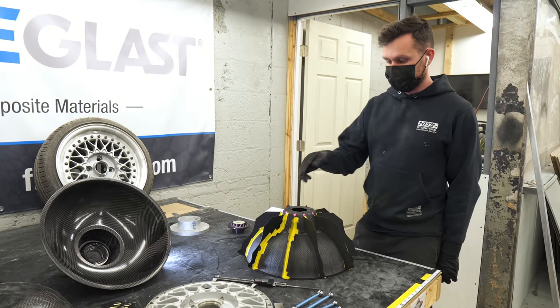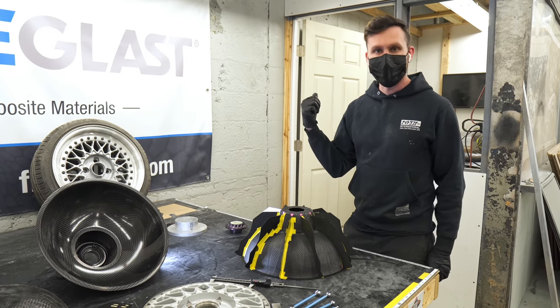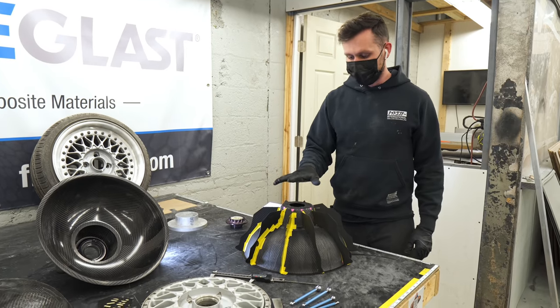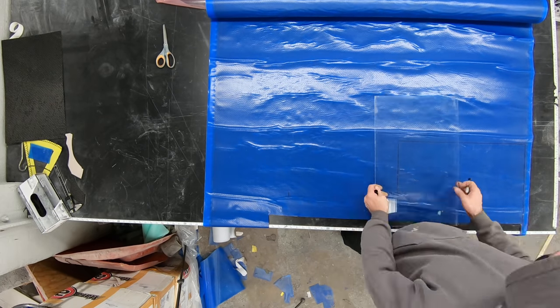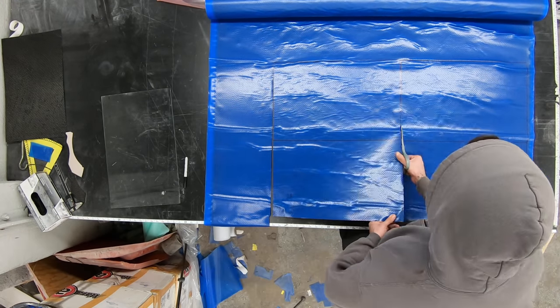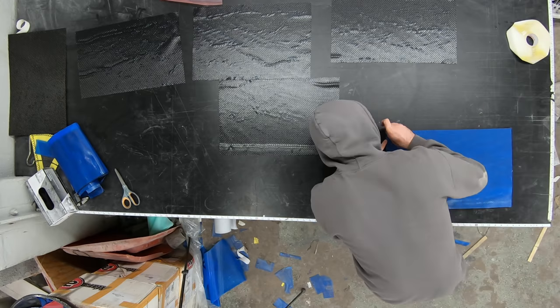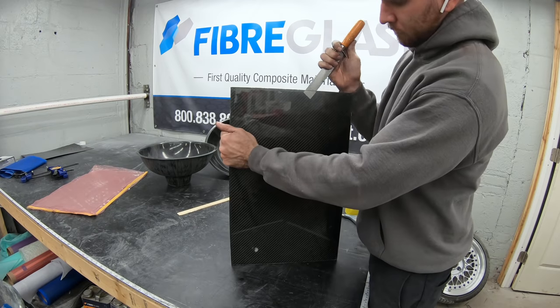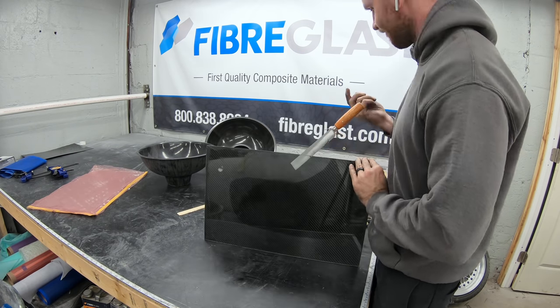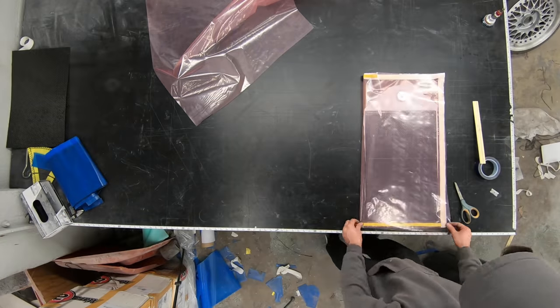These fins are going to help diverge the air. For the fins I needed a flat sheet, and since we'd never used the CNC machine before I figured it might as well be a carbon project. I found a piece of glass that's the perfect size — I could fit 10 fins on it — and I took six sheets thick of this 3K pre-preg carbon fiber from Fibre Glast. They sent us all this stuff just to experiment with pre-preg, which is usually very expensive. I took six layers, vacuum bagged it, and baked it again with the same cycle in the oven.